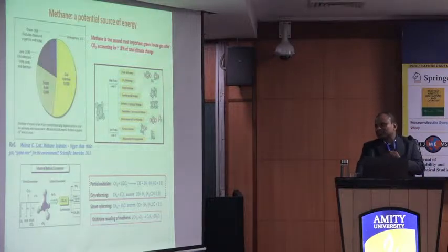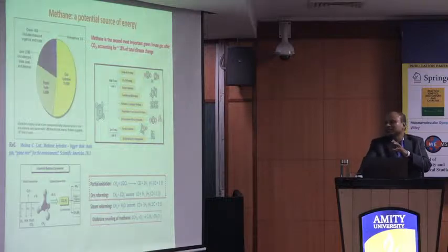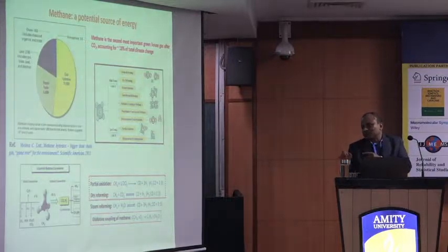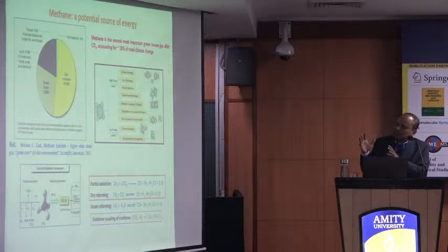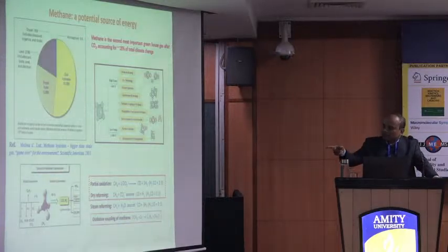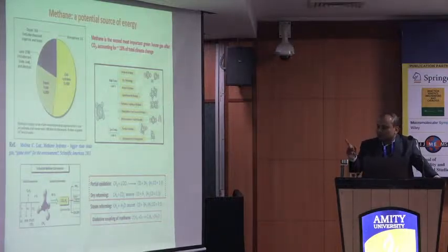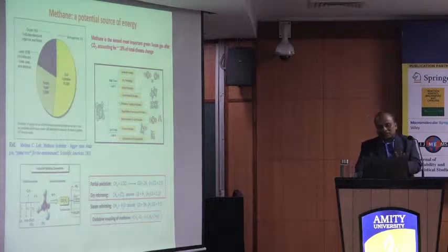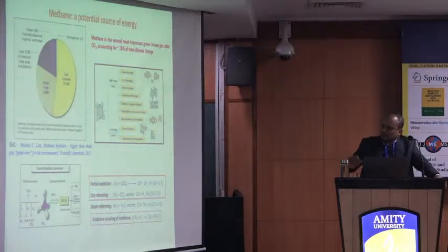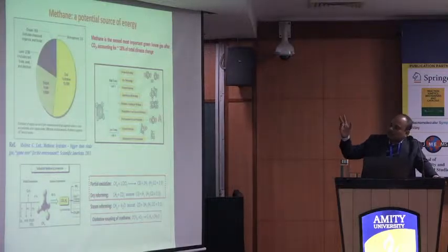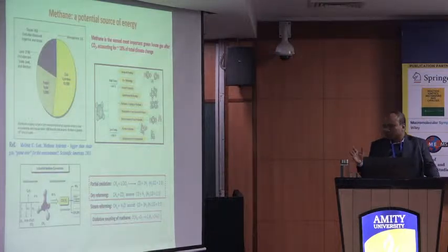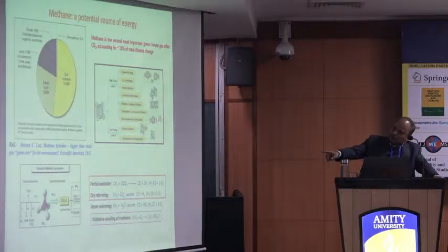These are the partial oxidation. This is important because this is the only exothermic reaction where we get syngas with H2 to CO ratio of 2:1, which is ideal for downstream methanol synthesis. Another is dry reforming, methane plus CO2 to give CO and hydrogen. This is an important reaction because two greenhouse gases, methane and CO2, are giving syngas. And there is also oxidative coupling of methane, where methane is directly converted to ethylene. But these are not commercialized so far, mainly because of the problem of catalyst deactivation. I will talk today mainly on partial oxidation, dry reforming, and oxidative coupling of methane.